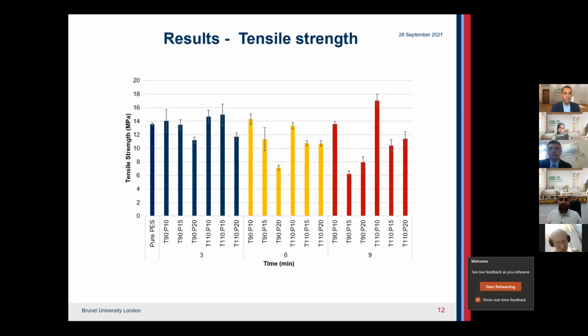So also looking at the tensile strength, although the flexural strength decreased on all aspects of using the filler, the tensile strength increased for the 3 minutes and for the 9 minutes for 2 different conditions. If we look at the diagrams, higher temperature showed a better enhancement on the strength of the composites. However, the medium, like for example, for the 9 minutes, the 15 tons showed the lowest drop in strength. So each parameter played a different role.